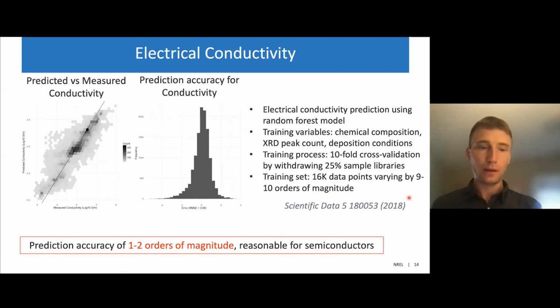Finally, we have applied or used the random forest method to predict electrical conductivity reported on a large number of semiconductors in our database. And we used both chemical composition, X-ray diffraction features, as well as deposition conditions for training this data set by tenfold cross-validation, which was around 25% of sample libraries.